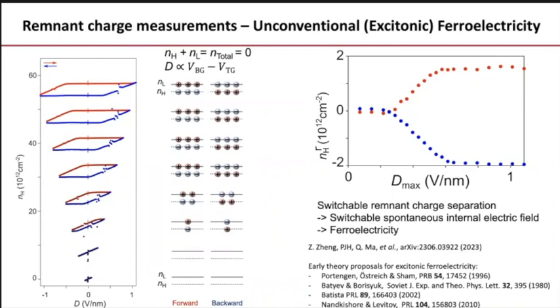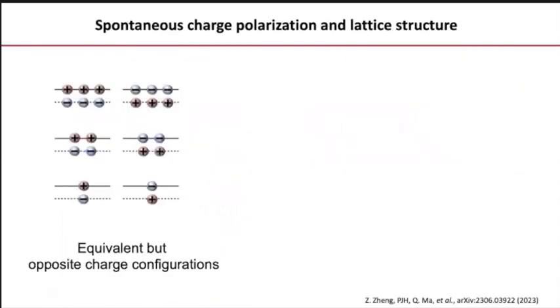For that, you need strong interactions, and you need these different characters of the charges. Although we're not sure that we realize that particular model, we have flat bands, we have itinerant and localized electrons, and we have strong interactions, and we think we're realizing that. Some people have told me, oh, but wait a moment, you're already breaking the symmetry to start with because there are different twist angles. Yes, but that is a weak symmetry-breaking structural field. I can flip between electric dipole moment up or down without flipping the structure; it's always the same structure. So the electronic system doesn't experience that symmetry-breaking field other than to orient the dipoles.